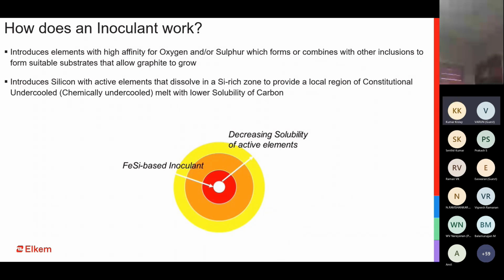Now, when the carbon comes out, it needs to have a favorable environment or a favorable situation for it to precipitate as graphite. And that is where the inoculating element comes into the picture. That is barium, calcium, strontium, zirconium, etc. So silicon ensures that the carbon does not stay in the system, it comes out. And the inoculating element ensures that this carbon which is coming out precipitates as graphite and does not again combine with the iron to form iron carbide.